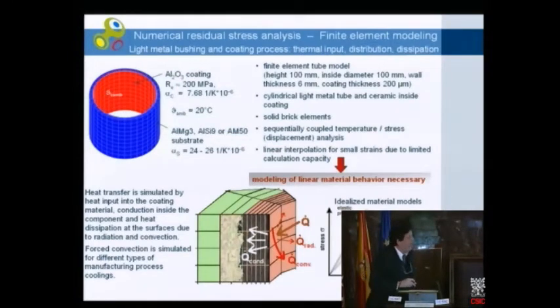Okay, so the first step we have to perform is to understand the behavior, the compatibility between our ceramic coating and the light metal substrate in this case. And you see the big difference in the thermal expansion of the two components, and it is not so easy in this case to use a plate. At least we start with a cylinder. I will show you more complex geometries in a minute.